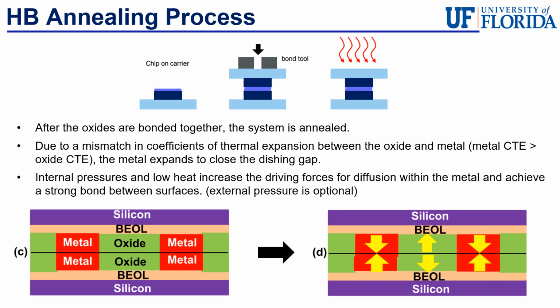Now, because the coefficient of thermal expansion of the metal is typically much greater than the coefficient of thermal expansion of the oxide, the dimensions of the oxide will remain relatively constant compared to the dimensions of the metal. And here in step C, the metal will expand due to the heat and it will close the dishing gap, bonding the metal pads of each respective wafer to one another.